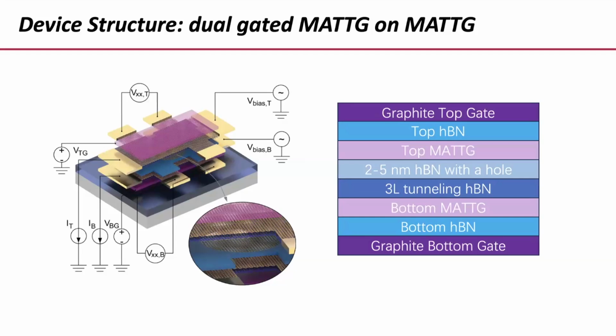So it's a dual gated structure. And then the active regions are two magic angle tri-layer graphene sheets, so two three-layer stacks: the bottom magic angle tri-layer and the top magic angle tri-layer. Separating these two sheets, there are three layers of hBN, about a nanometer in thickness. That's going to be a tunnel barrier between these two magic angle tri-layer sheets.